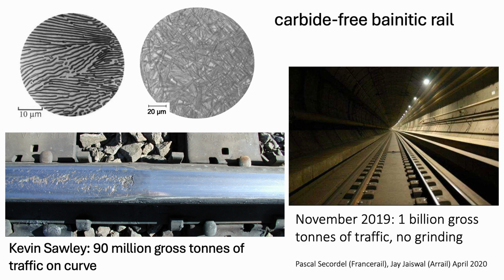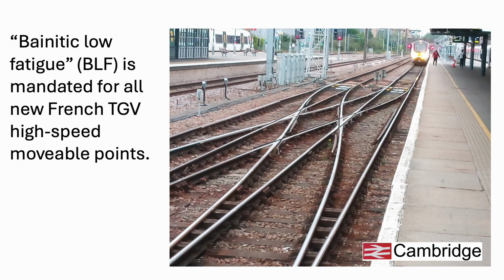You can see here the relative damage experienced by the pearlitic rail when compared with the carbide-free bainitic rail following 90 million gross tons of traffic on a curve. And the picture that you see on the right is the carbide-free bainitic rail installed in the Channel Tunnel, which in 2019 completed 1 billion gross tons of traffic with no grinding necessary. And about a year ago, the French authorities ruled that complicated points and crossings should be mandated to be made out of the carbide-free bainitic rail.